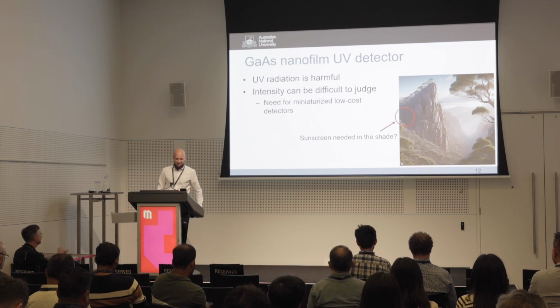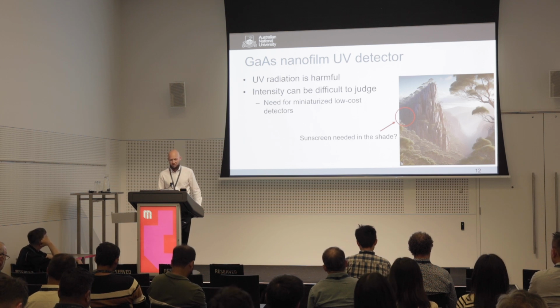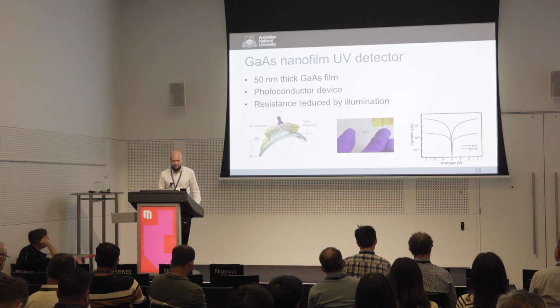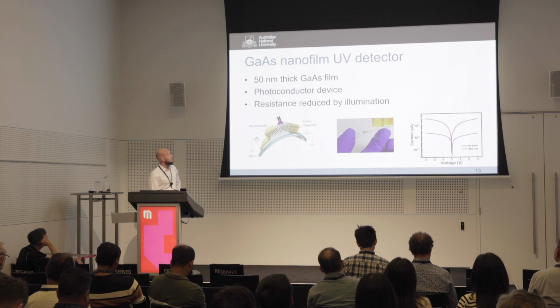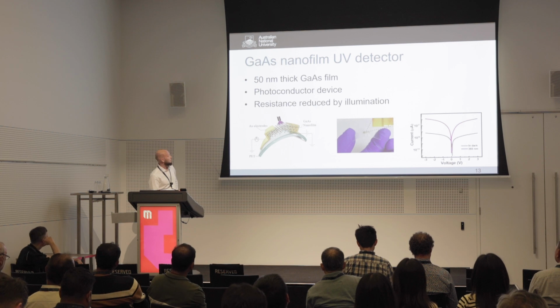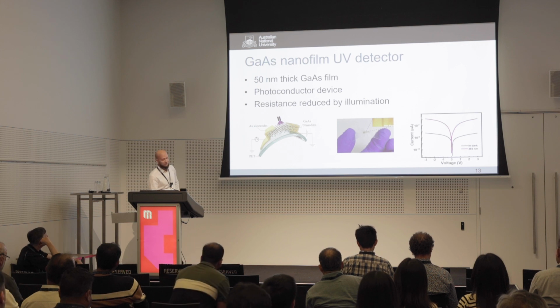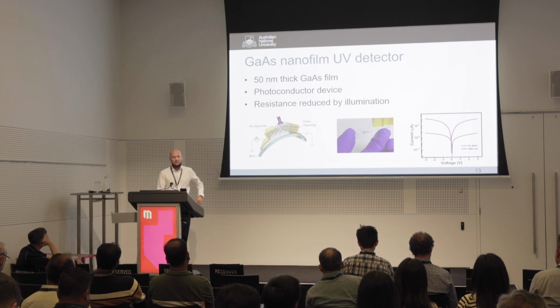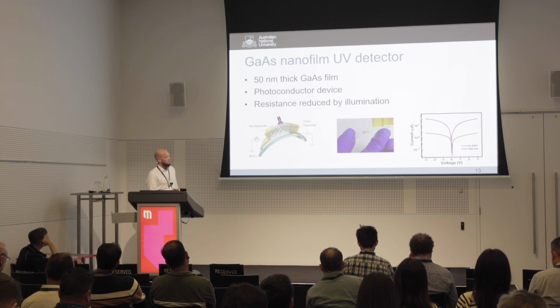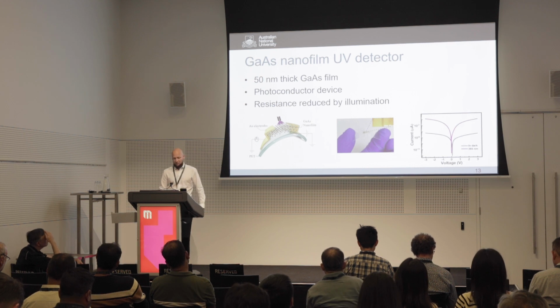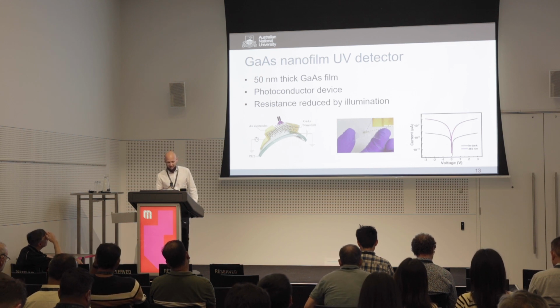So from this there arises a need for miniaturized low-cost UV photodetectors that can, for example, be integrated in wearable devices to track your exposure over time. So our device was made of 50 nanometer thick gallium arsenide film, and it's a photoconductor device, so we just measure resistance between 2 metal electrodes, and when we illuminate it with light, that generates charge carriers, and the resistance changes, which is shown here, so we can have a very clear response for UV light in the resistance.